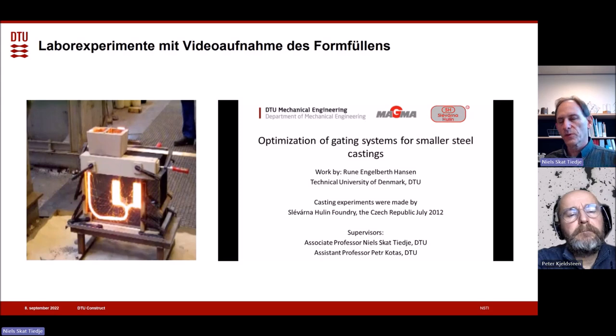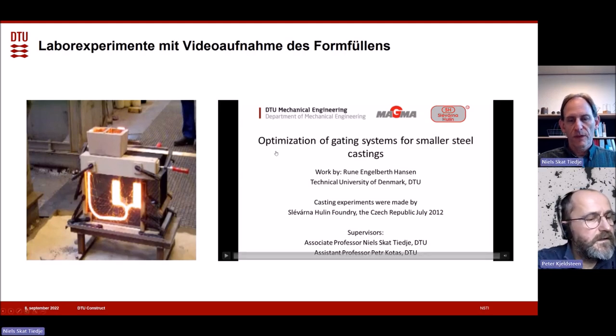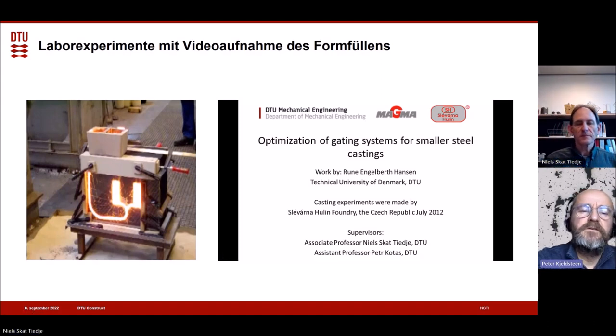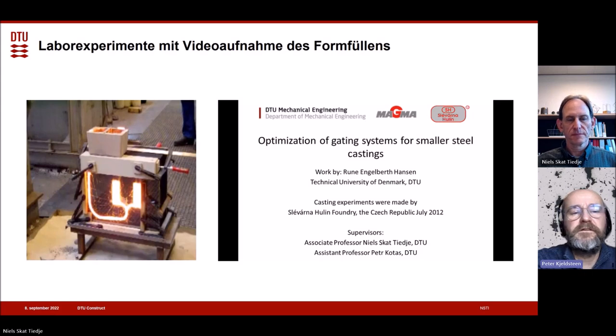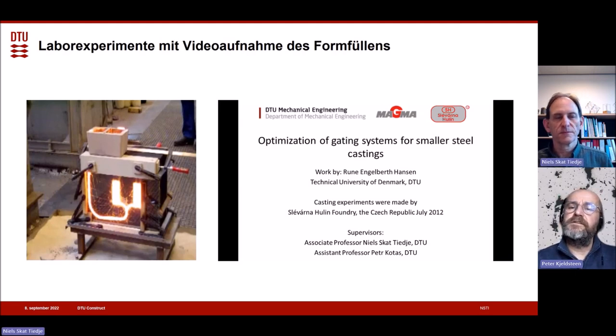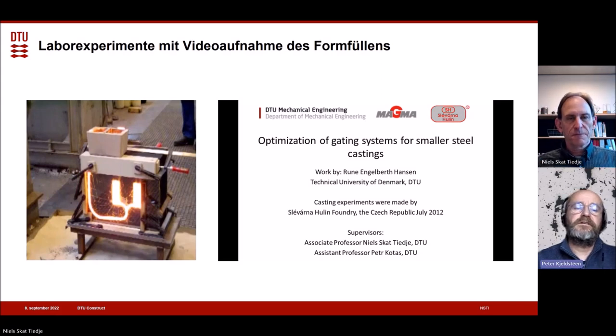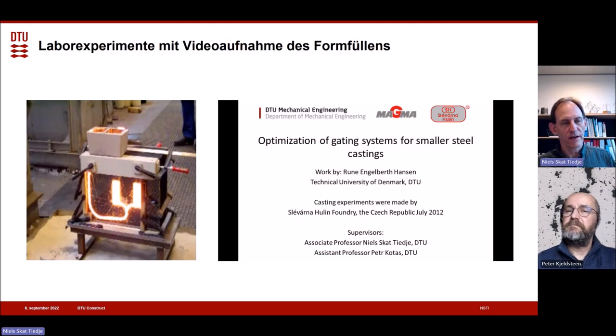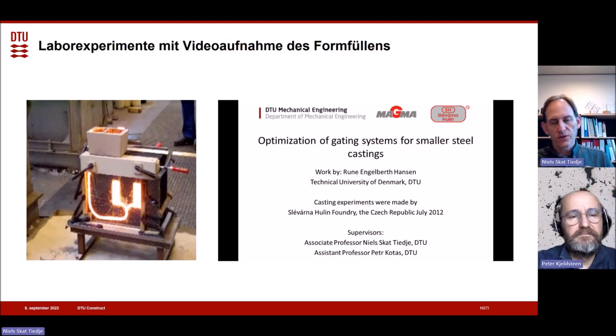So we did a lot of work on how to cast, but we also did a lot of work on the materials processing, the chemical composition, and also the melt treatment and things like that. And as I remember, when you solidify cast iron, the shrinkage is a function of how fast it solidifies, or what kind of microstructure you create. Exactly. You can control the shrinkage to a certain level, but if you solidify very fast in some place and very slow in other places in your structure, then you have two different shrinkage rates. Is that right? Exactly. Then you get solidification carbides. You get ledeburite, which is essentially white cast iron, and that shrinks like steel. Yeah. So you need the graphite to form and then expand. And I'll show a video a little later on how that goes.